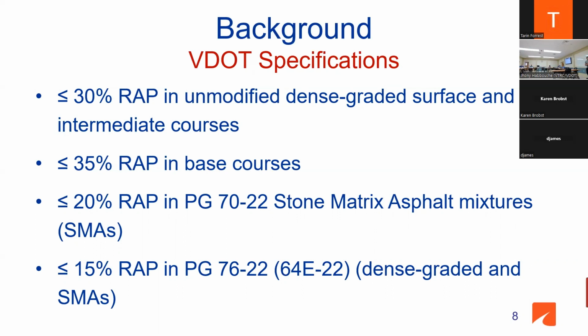So that's the VDOT specification. So now we're trying to take the first bullet, the 30% RAP, and push the envelope a little bit. Can we increase that 30% to 35, 40, 45, maybe up to 60%, while still producing a very good performing mix, short-term and long-term, in the lab and in the field, as well as taking into consideration the capabilities of the asphalt plant out there, because not all plants can go up to 45, 50% RAP.